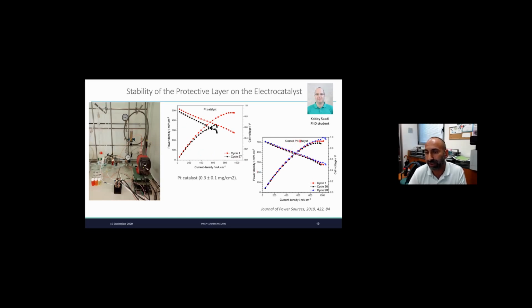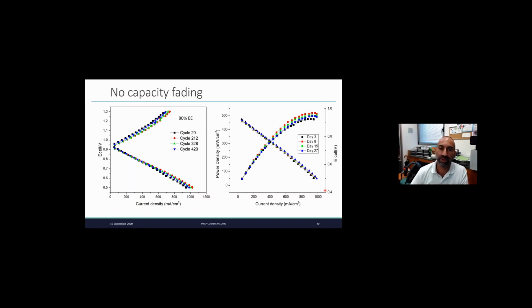And when we have this coated platinum catalyst, it's very stable for 100 cycles. And I will show you that it's also stable for even 1,000 cycles. So we did here for 420 cycles, and we don't have any fading of the capacity. The energy efficiency is about 80%, which is not too bad. And you see here in time, so after 27 days, this is the same. We don't run forever because we don't have the capacity to flow hydrogen forever in the lab for safety reasons.